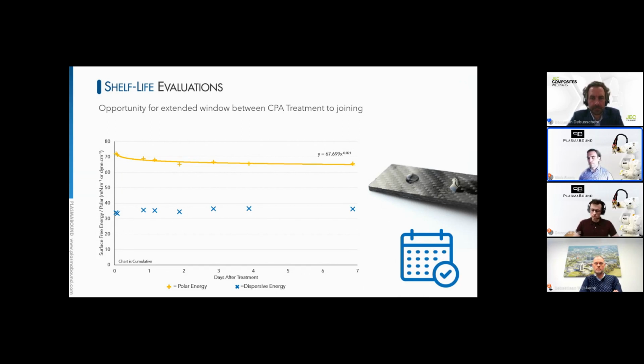Note also, the primary cause for decline is in the polar component, which is passivating over time. Essentially, the dispersive component of our treated surfaces remains relatively flat throughout the 7 days. So the decline is governed by the polar. This is a known effect, and it just means that the surface is slowly what's called passivating over time.